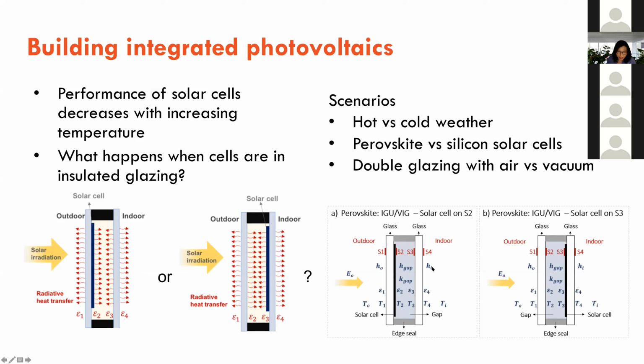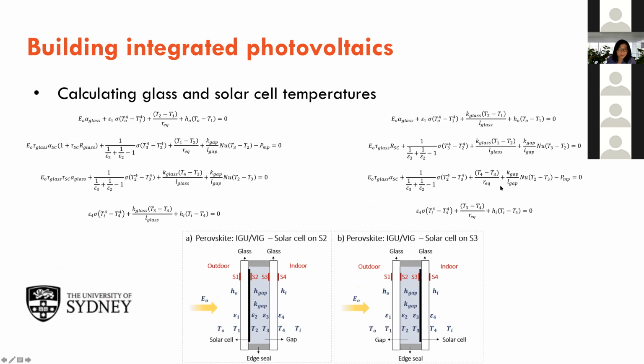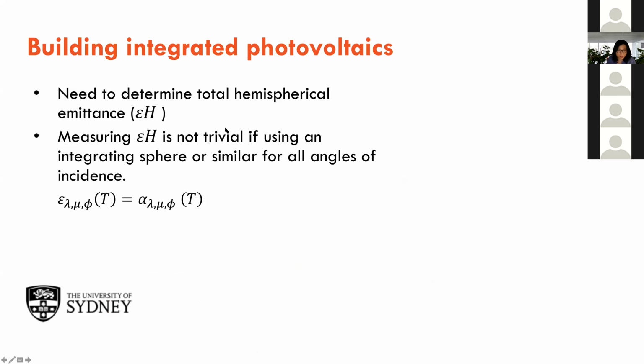So anyway, this is a whole bunch of elements that we need to take care of for the heat transfer calculation. We look at the different scenarios of the cells in hot and cold weather, perovskite versus silicon, double glazing with air or vacuum. And we found that to calculate the temperature, we need the emittance values. The emittance values are not trivial to measure if we decide to use the integrating sphere. Then you have to integrate all the values, all the angles.